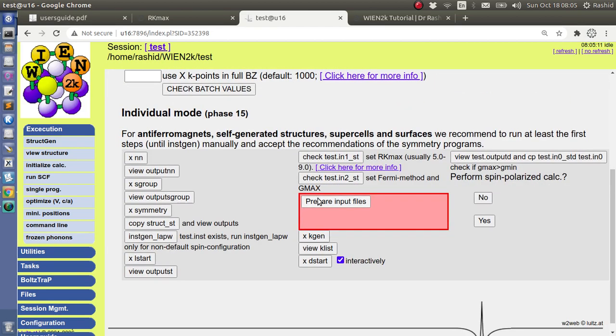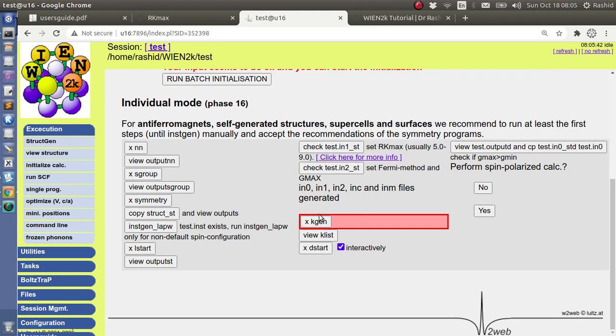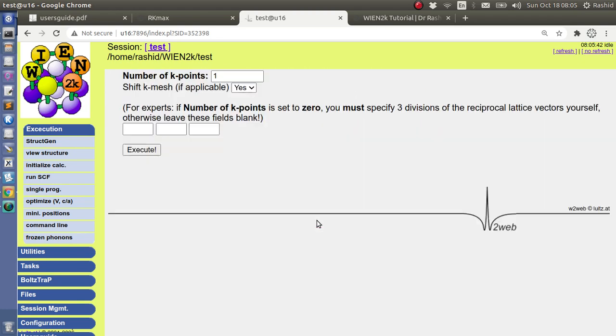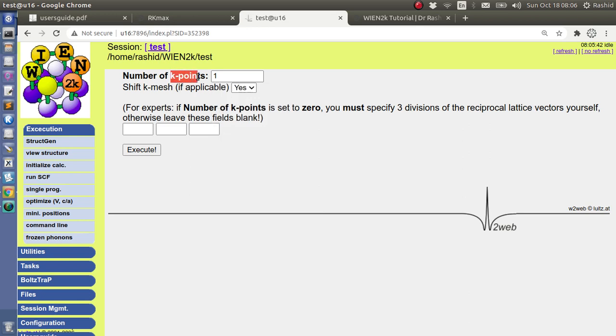So we will prepare the input file. It says that the input files seem to be okay. For the Kmax, actually we depend, the k-points depends on how the system is. What we should do is we should do the SCF calculation with different k-mesh and see when the energy becomes consistent with the change of k-points. So you start with a small k-points, say with 500, then try with 1000, then maybe with 5000 or something like that, whatever you choose. And you see at some point the energy value does not change, it will be a straight line.